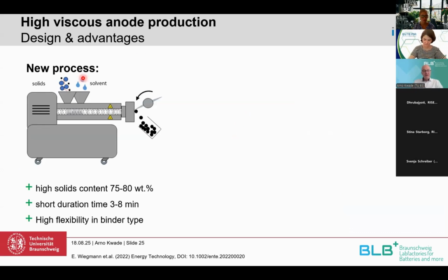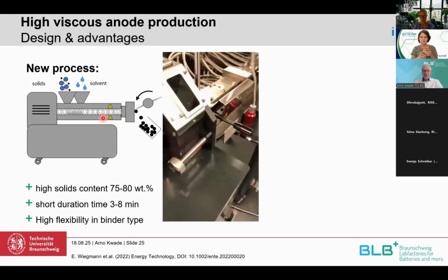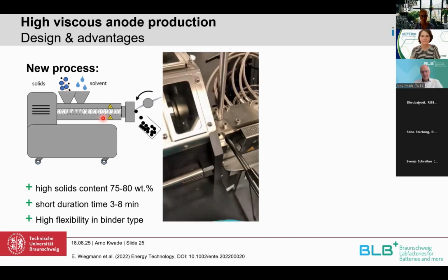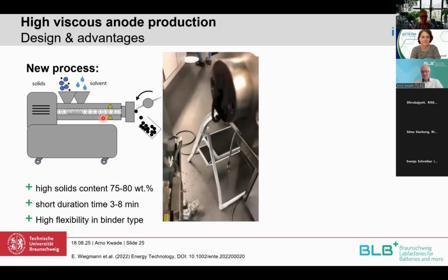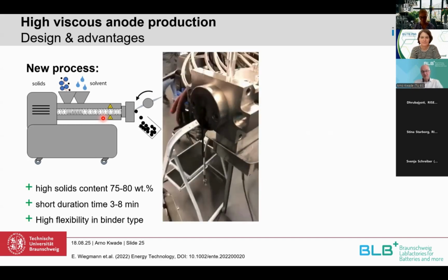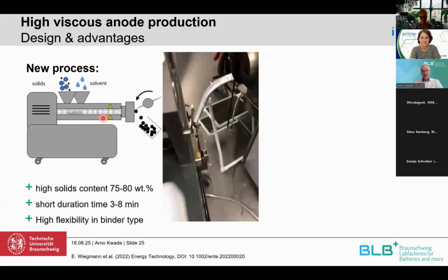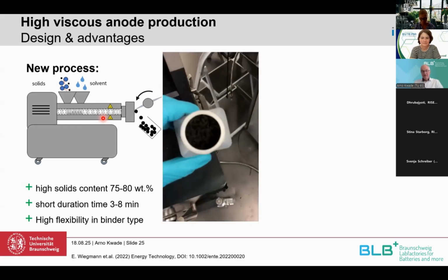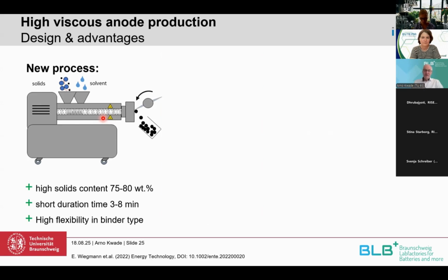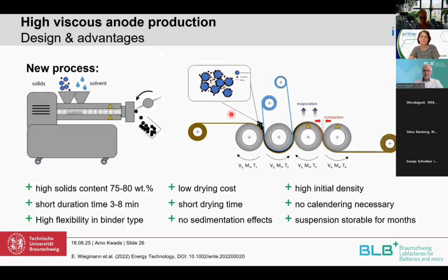The semi-dry coating is a new process which we developed at our institute. We use an extrusion machine, but it can also be a batch mixer, where we produce wet granules with a small amount of solvent. These wet granules, in this case, we got with a cutting knife, but there are also other possibilities to get wet granules without cutting them. They are in the size range of a few millimeters, and then we dose them on a multi-roll calender, in this case a 4-roll calender, and form the film similar to the dry coating process.